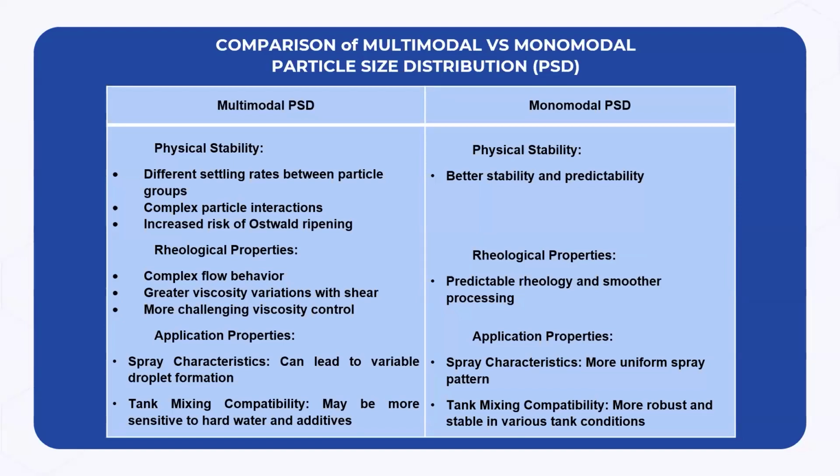Each type of PSD in an SC formulation may significantly affect product performance and processing efficiency. Physical stability. Multimodal PSD reduces stability in SC formulations due to varying settling rates, complex particle interactions, and an increased risk of Ostwald ripening, while monomodal PSD enhances stability and ensures greater predictability.